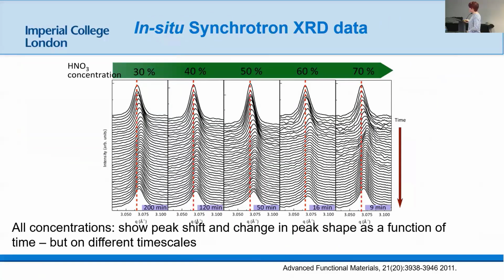And this is what you see. So we're just sitting on one of the diffraction peaks over time in different concentrations of acid. And again, this is nitric acid. So we're not just changing the pH, we're changing the oxidizing potential. So this one goes much faster. Right? In 9 minutes, it's pretty much dealloyed. I've got a shift in the diffraction peak and then a slow relaxation.